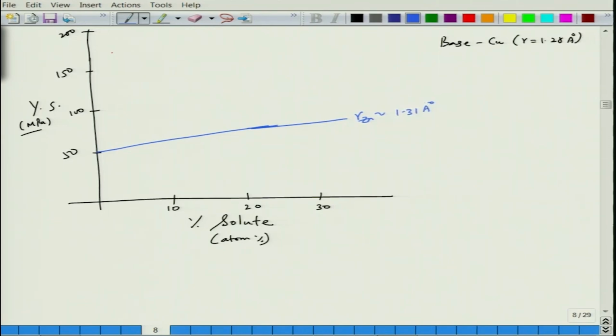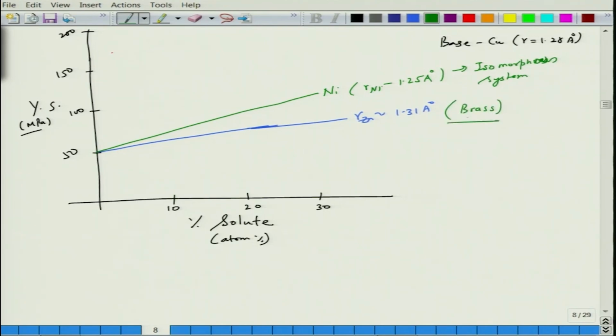So zinc has a certain solid solution strengthening effect. If you look at nickel to copper, nickel to copper is a very good example. Nickel to copper can lead to higher effects. So it can increase the values up to about, so nickel to copper will be somewhere here. This is nickel, and R nickel is 1.25 angstrom, very similar to copper. In fact, they make a nice substitutional solid solution, which is an isomorphous system. So it remains FCC all the way, whereas copper with zinc makes brass. So it has limited solid solubility. After this it forms second phases and so on and so forth.